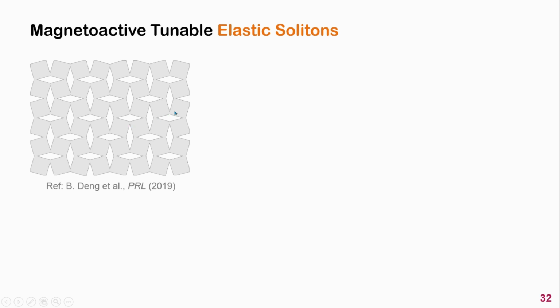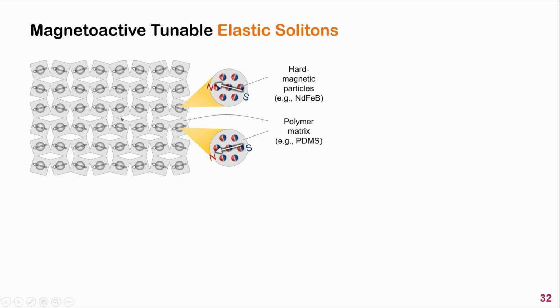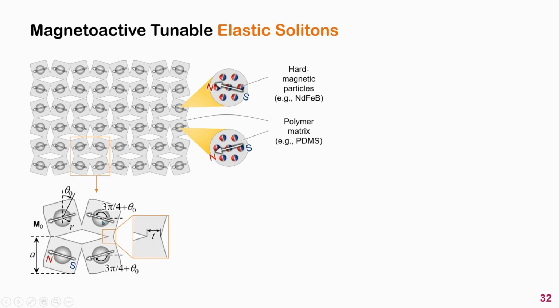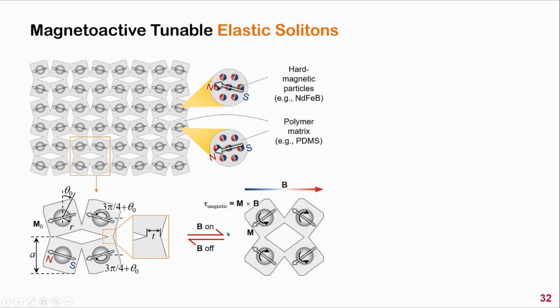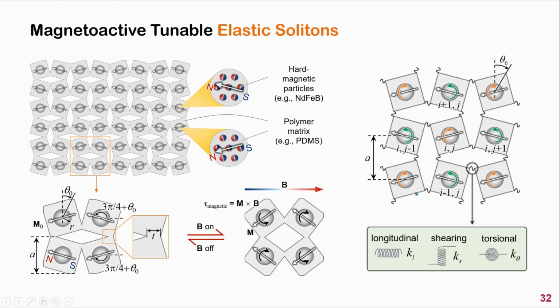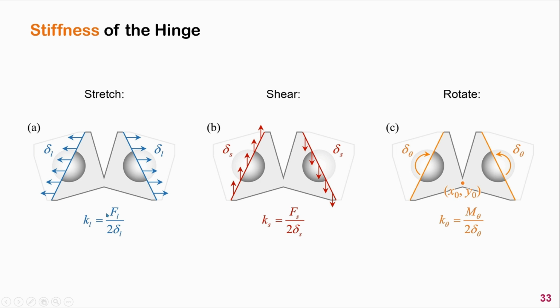Here, our idea is to introduce magneto-mechanical coupling into the purely mechanical system. In this manner, the microstructure of the system can be changed under external magnetic field, and we believe that this will finally change the solitary wave behavior of the system. Looking at the system, we can see that deformation will be highly localized at the thin hinge, and the hinge deformation can be modeled by using a combination of three springs, including the longitudinal, shearing, and torsional spring. And the stiffnesses of these springs can be determined by using finite element simulations of the corresponding hinge model.